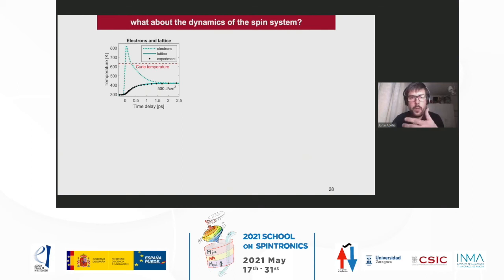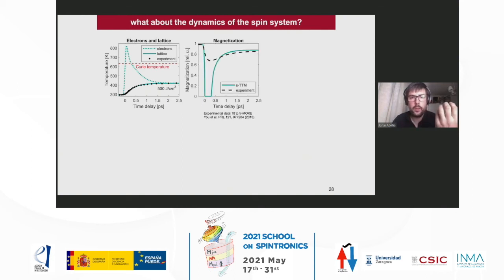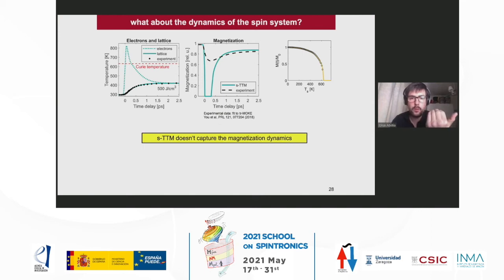If you look at the magnetization dynamics, what you could do is take what magnetization corresponds to this electron temperature. When the electron temperature is above the Curie temperature, the magnetization should be zero. If we look at magnetization as a function of temperature, when the temperature is above 630, magnetization should be zero. So this model doesn't capture the magnetization dynamics.